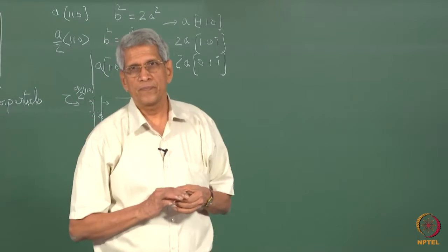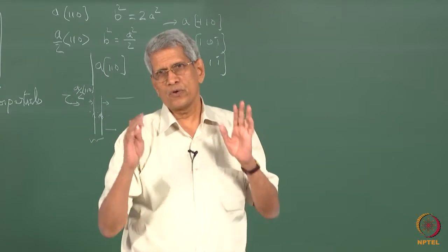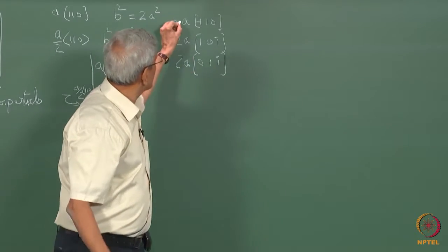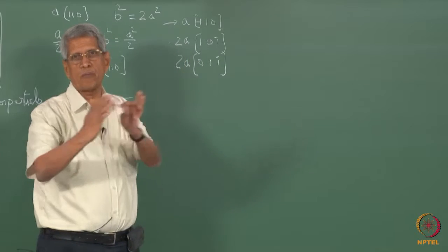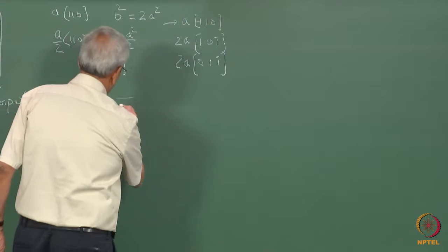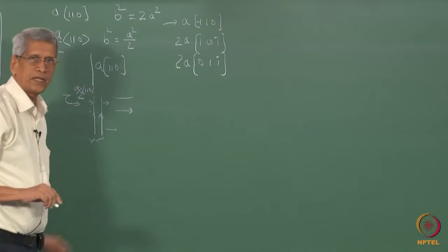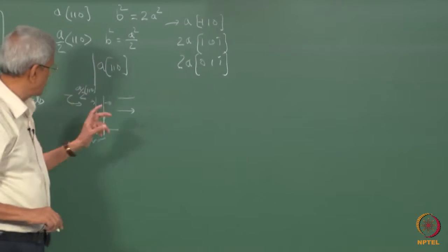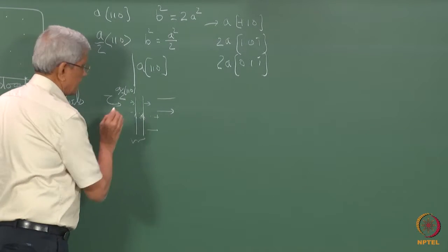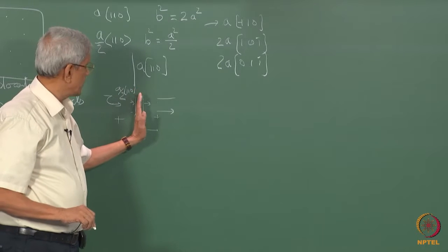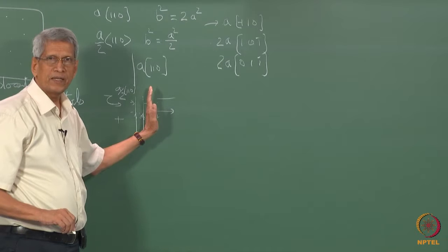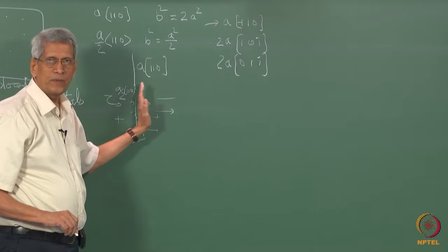That means in this particular direction, when 2 dislocations have passed through the region, this is the one direction in which the dislocation is moving, 2 partials are there. In this region as well as in this region, it is perfectly ordered. APB is between them. The first dislocation creates an APB, the second dislocation removes it, so that is how it moves.